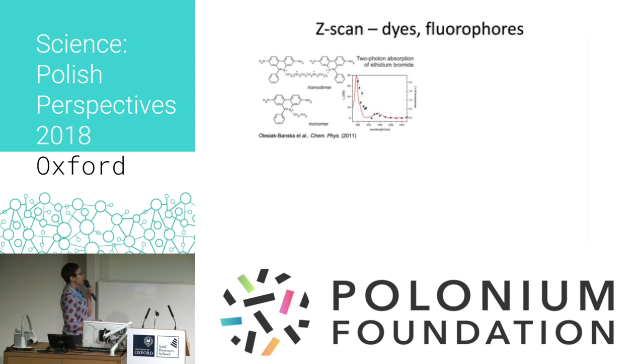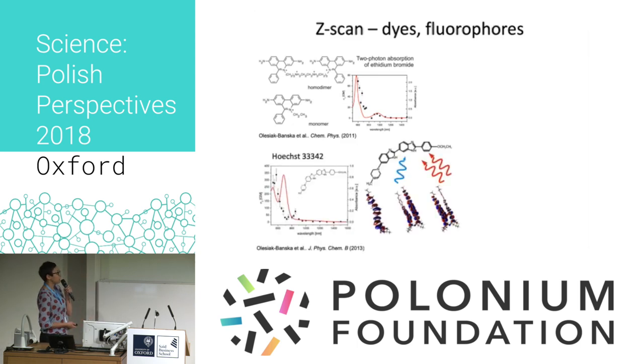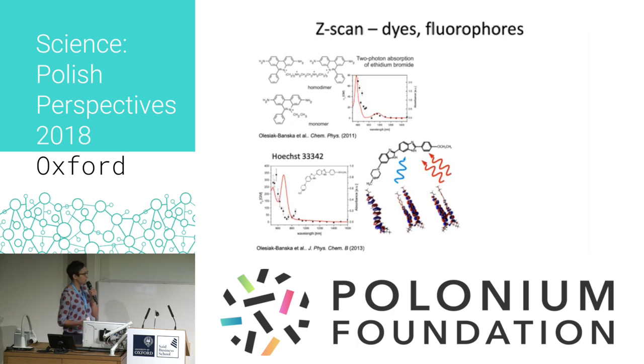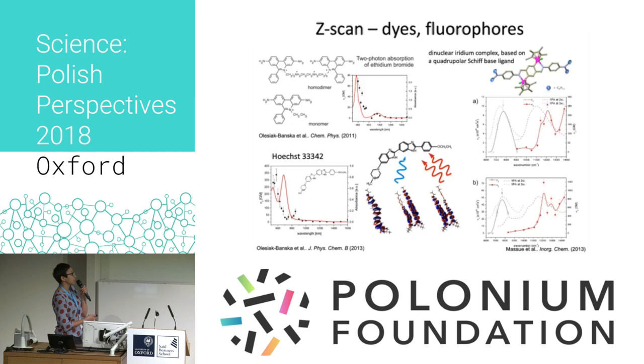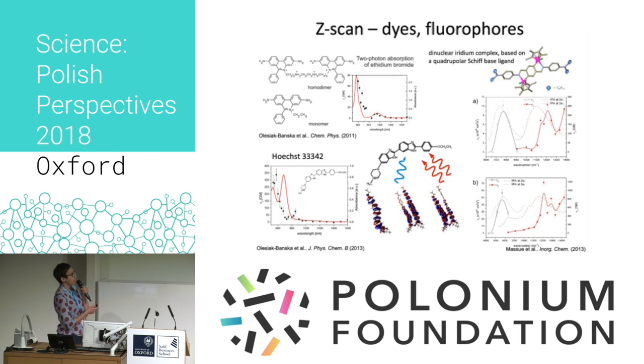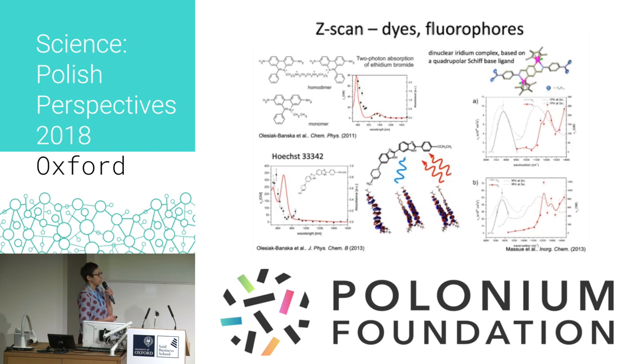With the Z-scan technique, I investigated two-photon properties of DNA-binding fluorophores such as ethidium bromide and Hoechst dyes. We did experiments across a broad range of wavelengths, collecting whole two-photon absorption spectra of these molecules — which is not very common, as it is quite time-consuming and tedious work. I also investigated more sophisticated molecules designed to be very good two-photon absorbers. For example, we proved that introducing iridium ions into quadrupolar molecules gives roughly one order of magnitude increase in two-photon absorption cross-section — from around 200 Göppert-Mayer units to thousands — and you can also observe three-photon absorption in such complexes.